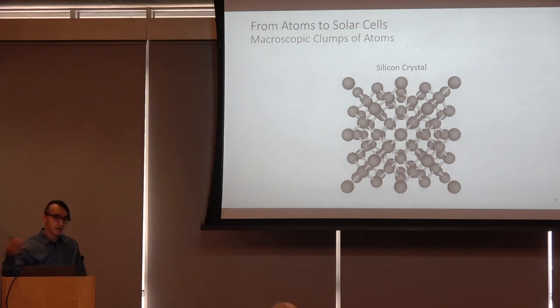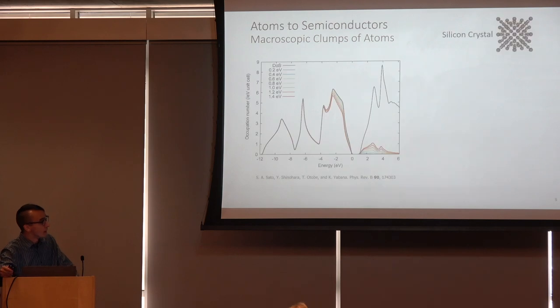Now, as we keep adding more and more atoms, you get more and more orbital mixing, up until the point where you get macroscopic clumps of atoms, things that you can actually see. That was a silicon crystal. Now, instead of having these sort of discrete transitions, once you've mixed enough orbitals, the gap between those energy levels becomes effectively zero, and you get what is called the density of states. Now, all materials have a density of states, but there's some key features here.